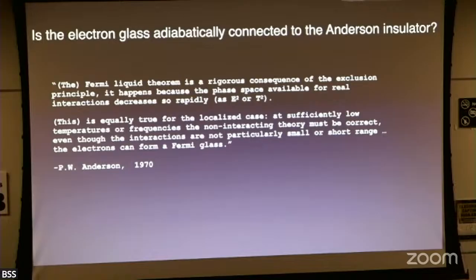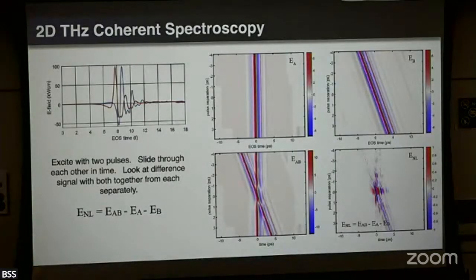In magnetic insulators, like that cobalt niobate that I showed you, I showed this plot with this kind of 2-peak structure, which I said was like a 1D density of states. That's a material which is an electrical insulator with a band gap of 3 electron volts. And so there, in a thick sample, we have weakly interacting spins, weakly interacting with the magnetic field of the terahertz. So it could be that magnetic spin physics is interesting here, but I don't see where it comes in, but I'm happy to have that discussion. Let's look at the data.